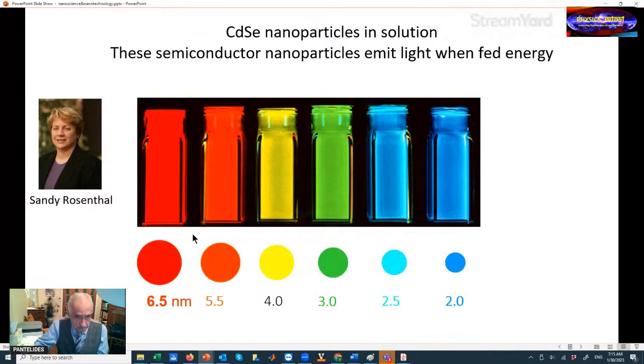This is another example of research that was done by Sandy Rosenthal, a chemistry professor here at Vanderbilt: cadmium selenide nanoparticles in solution of different sizes. If they are 6.5 nanometers, so we are getting very small now, very nano, the color is red. Then at 4 nanometers, it turns to yellow. And you can see the colors of the rainbow, right? Then you go to green, light blue, and dark blue at 2 nanometers. They tried very hard for a long time to make nanoparticles smaller than 2 nanometers, and it was very difficult. They expected, of course, to get darker blue or purple at the end of the rainbow colors.